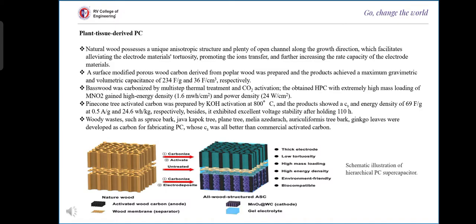Basswood was carbonized by a multi-step thermal treatment and carbon dioxide activation. The obtained HPC with extremely high mass loading was used to obtain high energy density and power density. Pine cone tree activated carbon was prepared by KOH activation at 800 degrees Celsius, and the product shows a specific capacitance and energy density of 69 F per g at 0.5 A per g and 24.6 watt-hours per kg, respectively. Besides, it exhibits excellent voltage stability after holding for 110 hours.